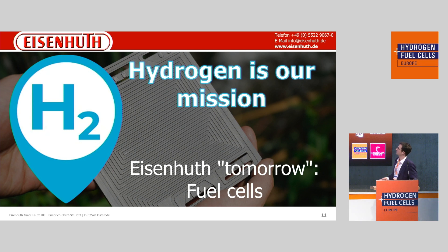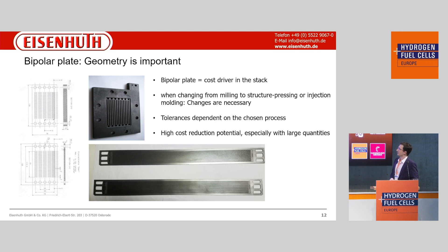Looking at what we can expect in the future for fuel cells — geometry is absolutely critical for bipolar plates. The flatness of the bipolar plate must be very good; there should be no tolerance variations in thickness between the corners or the middle of the plate in the flow field. If the membrane sits smoothly on the surface, we achieve good efficiency in the stack application.